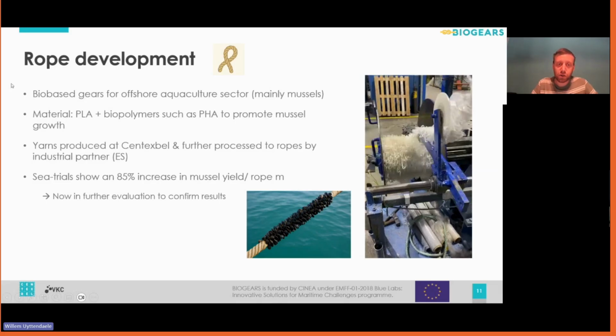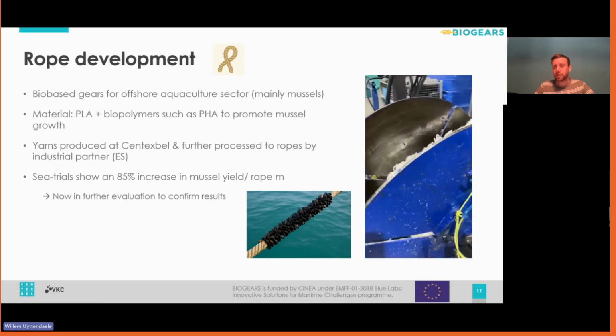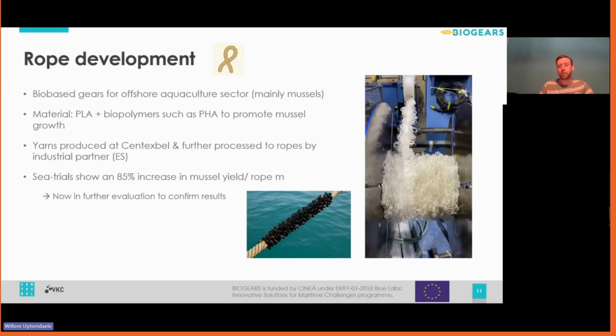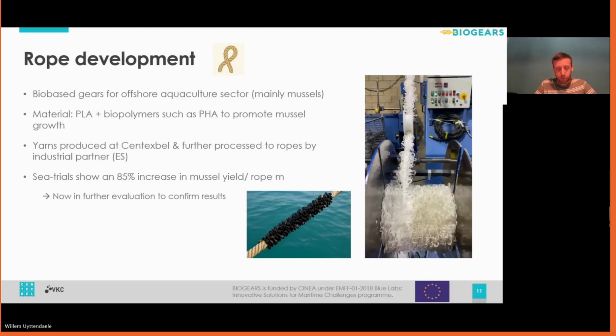Another development was for offshore aquaculture. What we think of here mainly is mussel growth, and mussels grow on these kind of ropes that are put down in the sea, commonly using synthetic materials, but it's quite interesting to look at bio-based and biodegradable materials for these ropes as well. And what we noticed here is that we could indeed make these ropes out of PLA in a blend with biopolymers such as, for example, PHA, and actually promote mussel growth. What we saw in sea trials is that we actually had an 85% increase of yield for these mussels on these bio-based ropes. Currently they are still in the final stages of evaluation, but there are quite interested parties to maybe continue with this development.